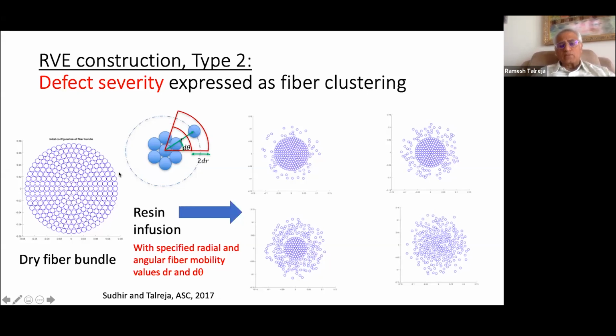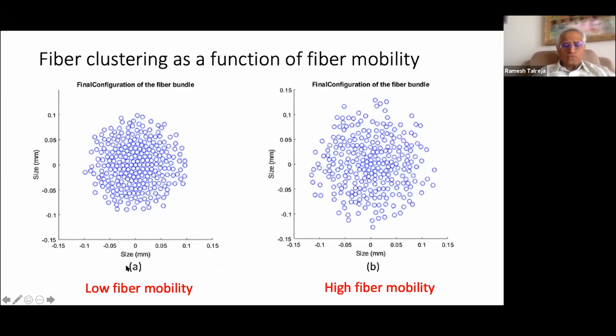And if you give increasing mobility, it of course will spread out more and have fewer clusters. So the algorithm, which is described in the paper there, spreads out the fibers from the outer regions. So as you proceed, you keep doing that until you come to a point where the distance from the central fiber to its neighbor is a certain minimum prescribed distance, because you want to have some resin there to put finite elements in there, minimum 2. So this is the pattern that you generate when you specify those mobility quantities, dr and d theta. Here's an example of a low fiber mobility, and you see it's very clustered. With a high fiber mobility, it's less clustered and begins to have resin-rich pockets. So that's sort of the idea.